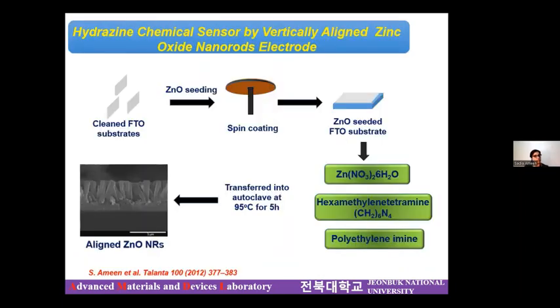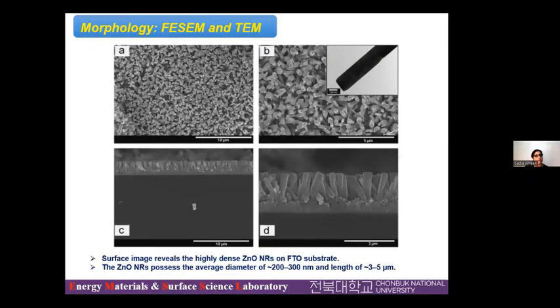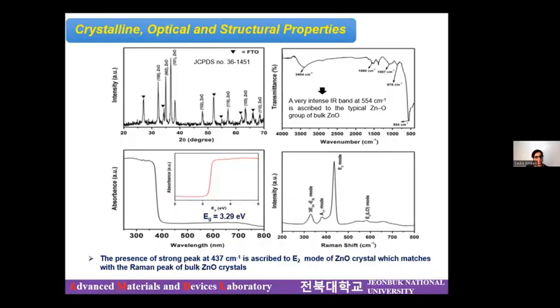And the next metal oxide that we have used is ZnO, which is zinc oxide. And here we have got an interesting morphology of zinc oxide. That is, these are aligned nanorods over the surface of the conducting FTO. And from the morphological images, it shows that the diameter is roughly about 200 to 300 nanometer, and the length of these nanotubes or rods is 3 to 5 micrometer.